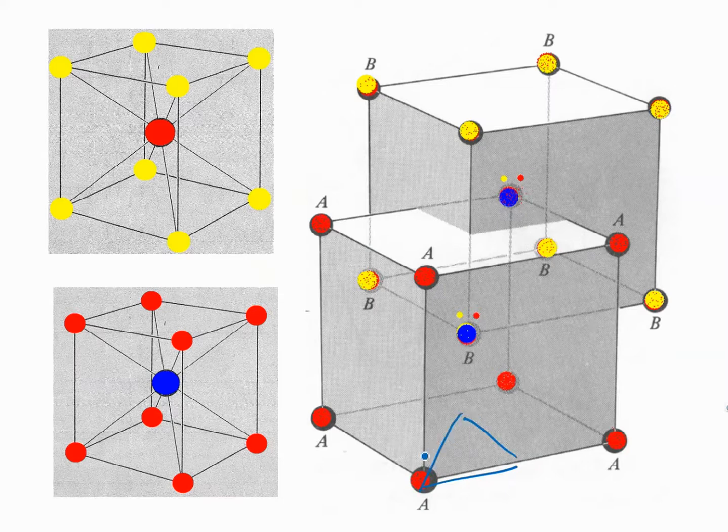So here to here is the hypotenuse. Then from the middle to here is half a, and you can get another hypotenuse. So you can get the distance between the center lattice point and the corner lattice point. For cesium chloride, this is the nearest neighbor distance.